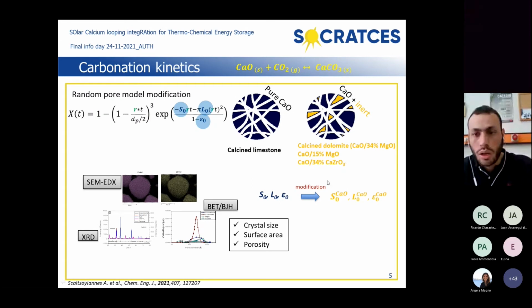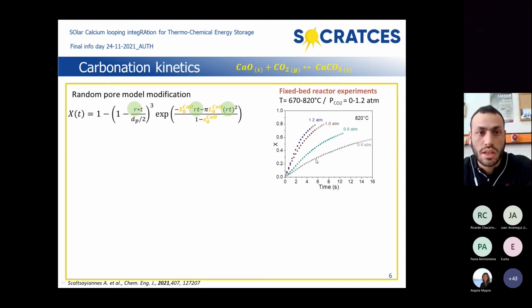So we introduced new input parameters, which included information from the scanning electron microscopy analysis, X-ray diffraction for the crystallite size of calcium oxide in the inert phase, and of course the surface area and porosity from nitrogen porosimetry. So in the general case, we use these modified parameters as input in the model, and again fitted this equation to the conversion time curves.